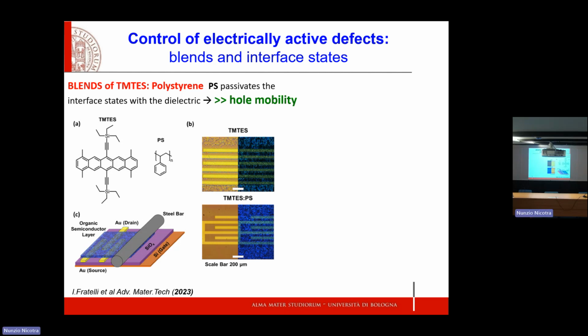Now, here I'm showing you another molecule that we are using, TMTES, and we used it blended with polystyrene. You make the blend very nicely, easily in your lab, in a beaker. You blend them, and then you deposit them using a steel bar, like a little brush. You use them to coat what? A substrate that contains a silicon gate, a dielectric, and metal electrodes. So it's a bottom gate transistor that you fabricate here by depositing this organic semiconductor layer. This is what you obtain in terms of polycrystalline film.